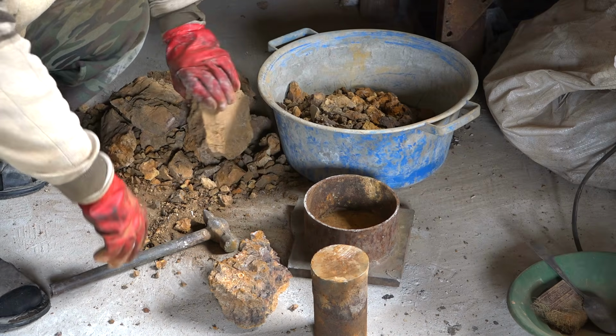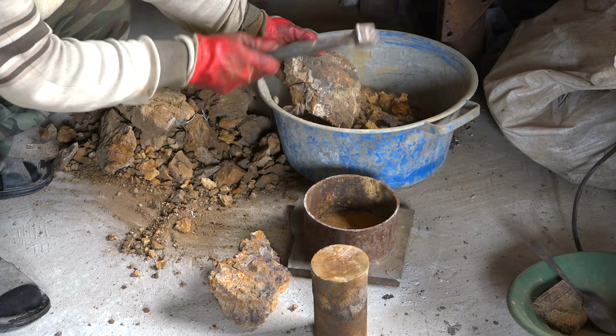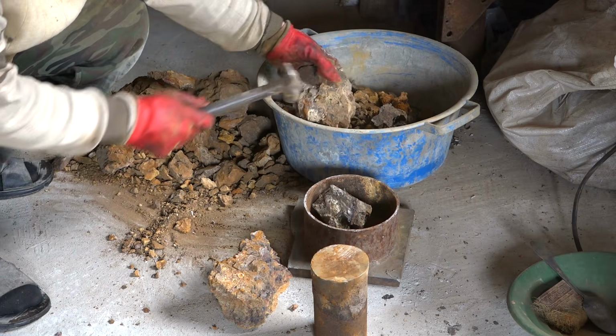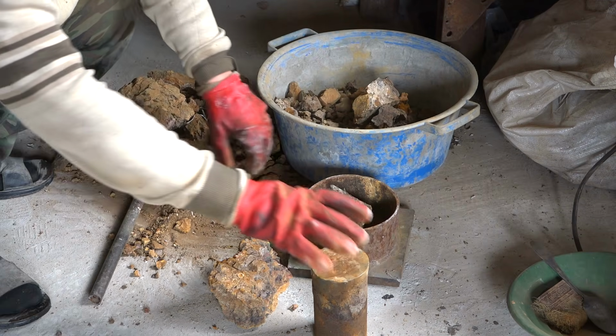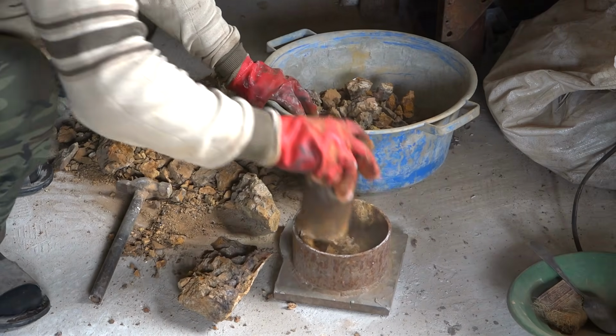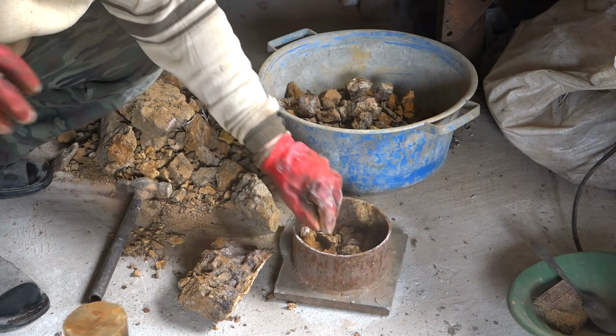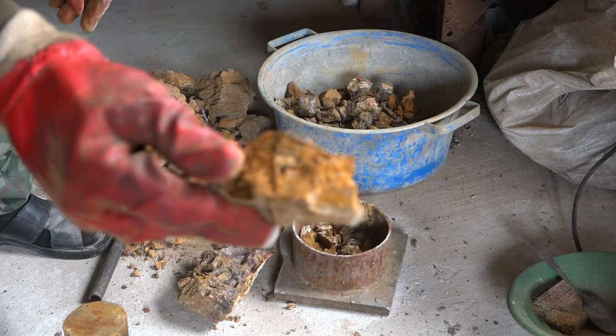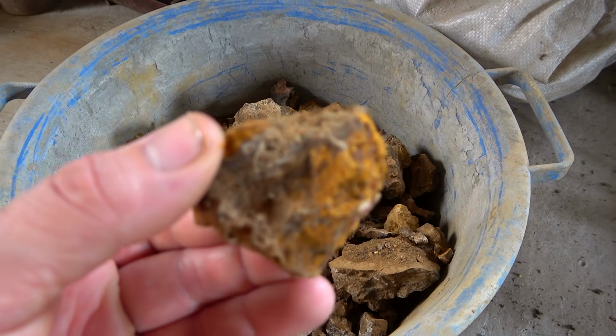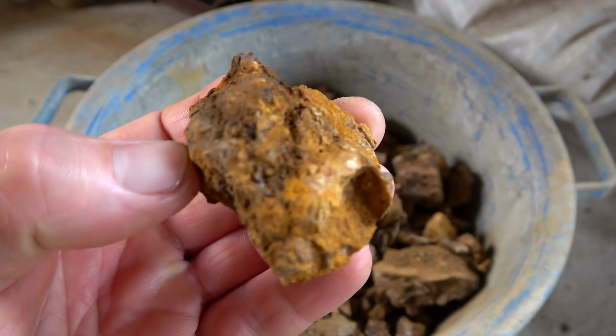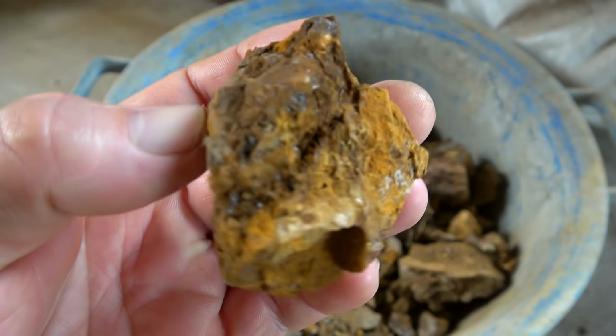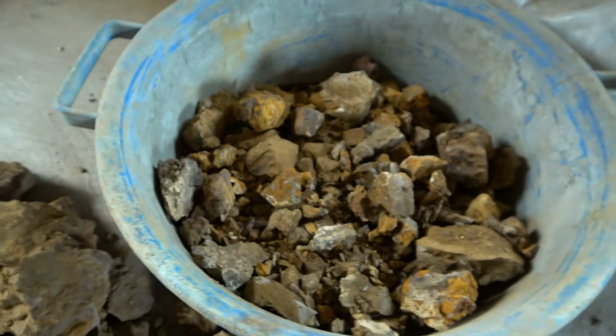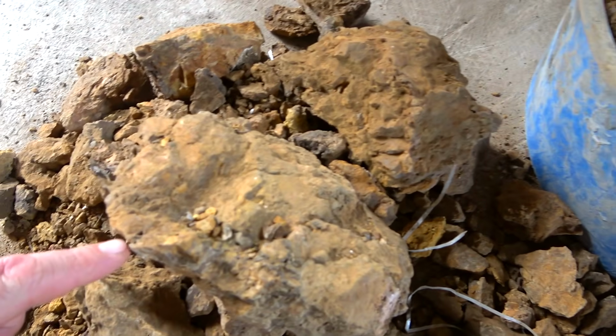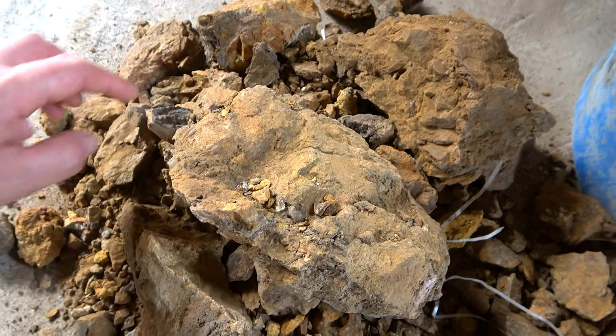Right now, I'm just crushing the ore. Due to the high mineralization, the stone samples literally crumble. Examine the ore carefully. It contains a lot of iron and lead, and some samples even show traces of copper. Gold content can range from 1 gram per 100 kilograms of stone or more. This ore also contains large amounts of magnetite, which makes washing the crushed ore difficult.